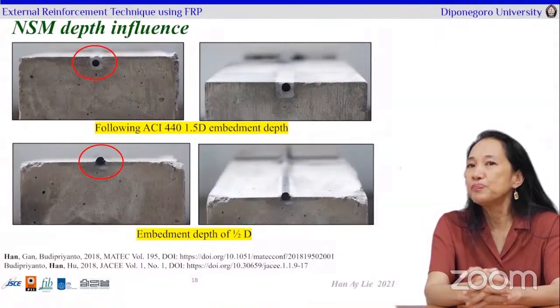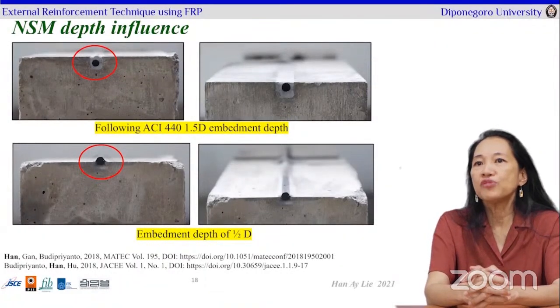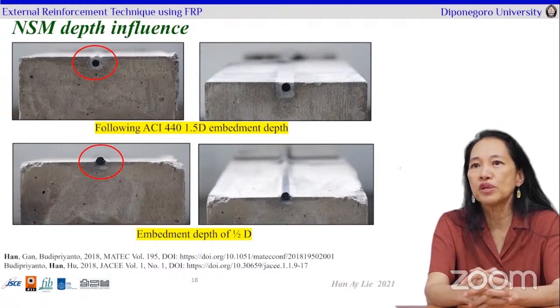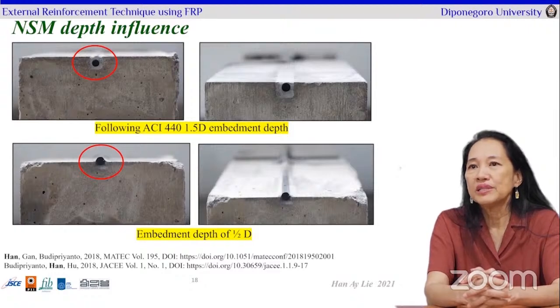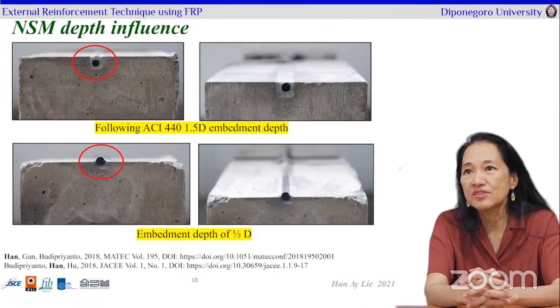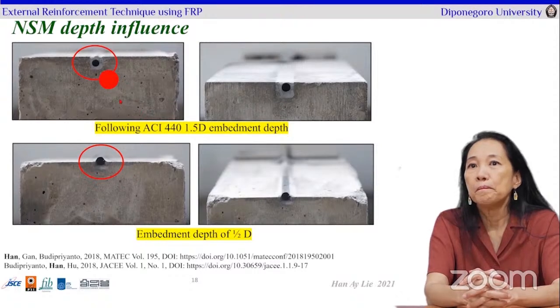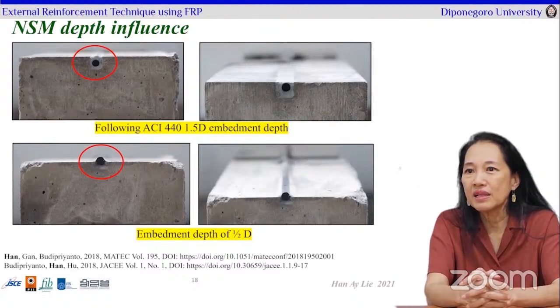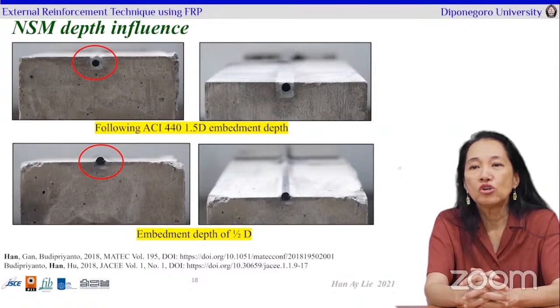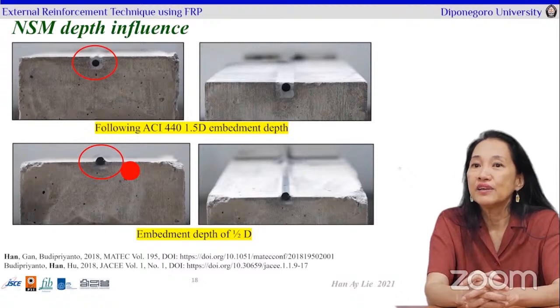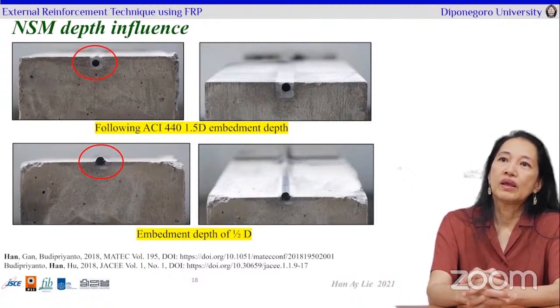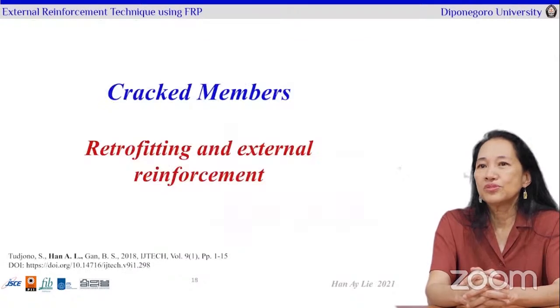Okay, now for the cover problem, the ACI 440 mandated a 1.5 diameter embedment depth. As you can see, that's the right one on top. But if you have not enough concrete cover, you can only plant it or embed it probably for half a diameter. So we tested the impact of these 2 cases and evaluated the results. So now we can go to the results.